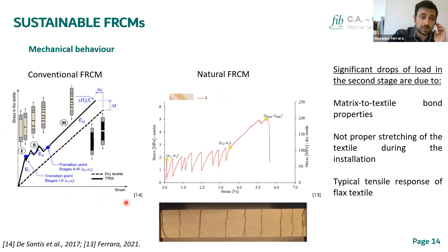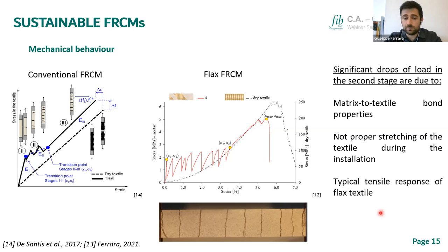So talking about the overall mechanical behavior of the composite, here we have a typical stress strain response of a conventional FRCM, in which we have the classical three-stage behavior. If we compare a typical tensile response of natural FRCMs, we can see there are some analogies, similitudes, between the two types of responses, but we can also observe that we have large deformability in the second stage, and we have significant drops of the load. These aspects are mainly due to the matrix to textile bond properties, to a not proper stretching of the textile during the installation, and to the typical tensile response of the flax textile. And in fact, if we look at the tensile response of the dry textile, we can see that the overall response follows this kind of response of the textile.